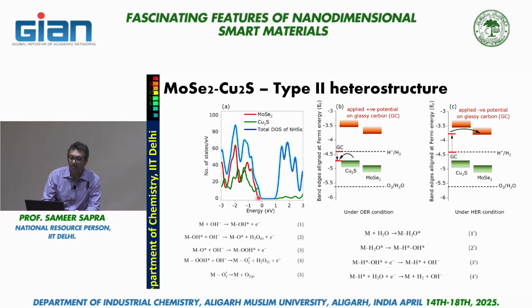See, it does not have any density at the top of the valence band, whereas the green one, because of copper sulfide, has a density at the top of the valence band, right? The red one over here has density at the bottom of the conduction band. Molybdenum selenide has density at the bottom of the conduction band. It's overlapping with the blue one, the red thing. The green one doesn't have, which is cuprous sulfide. This is exactly a type 2 kind of a heterostructure.